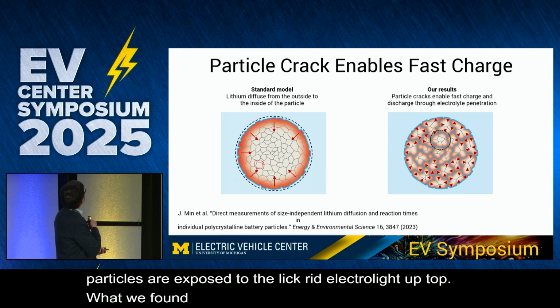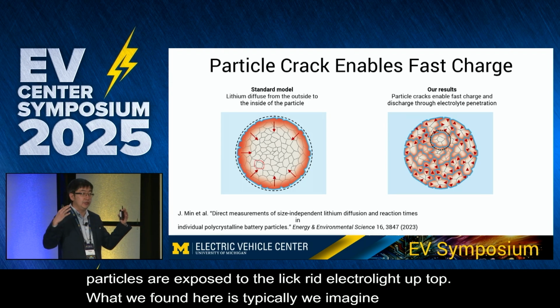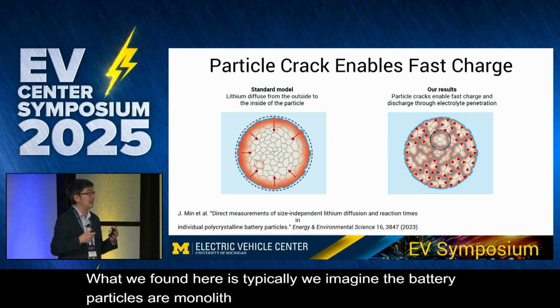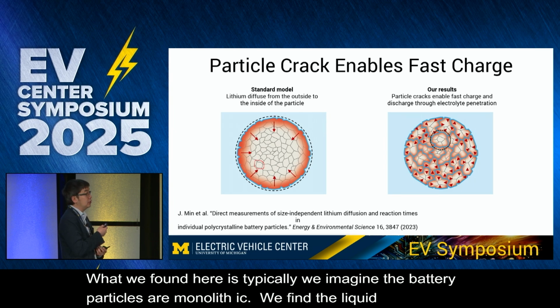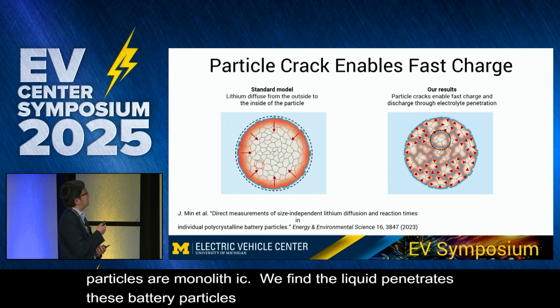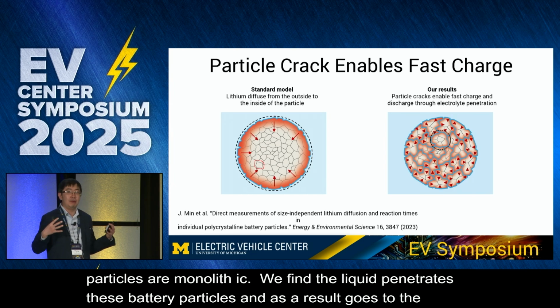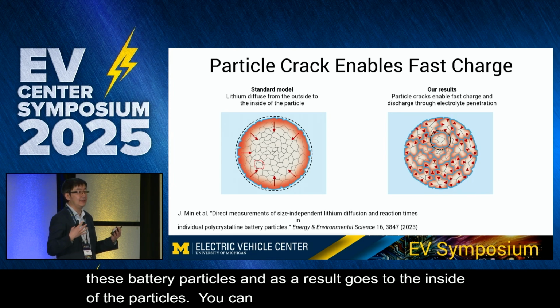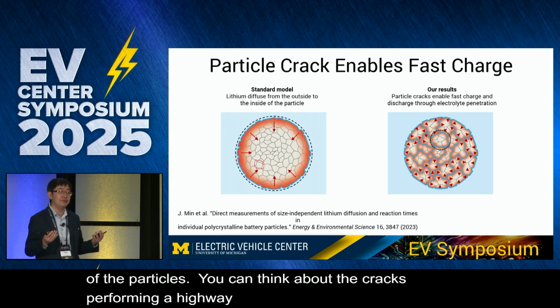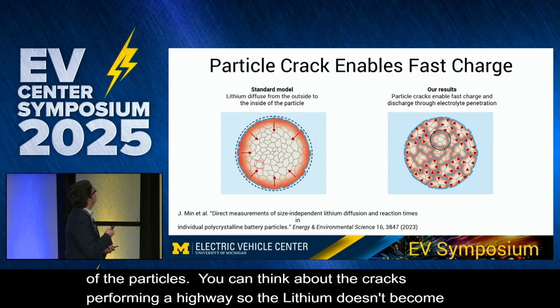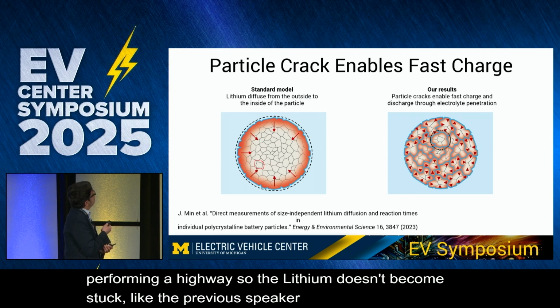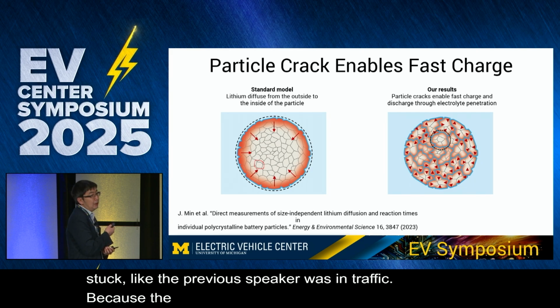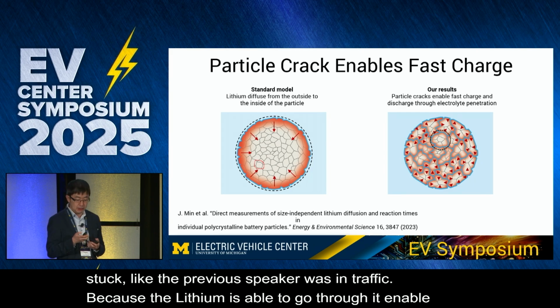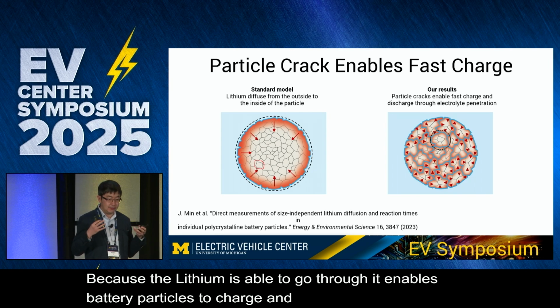So what we found here is that typically we imagine that the battery particles are monolithic. Basically, you get lithium diffusion from the outside to the inside. But instead, what we find is that the liquid penetrates these battery particles. As a result, it goes to the inside of the particle. So you can think about these cracks as forming a highway so that the lithium doesn't become stuck like the previous speaker was in traffic. Instead, because the lithium is able to go through it, it enables these battery particles to charge and discharge much faster because of the electrolyte penetration.